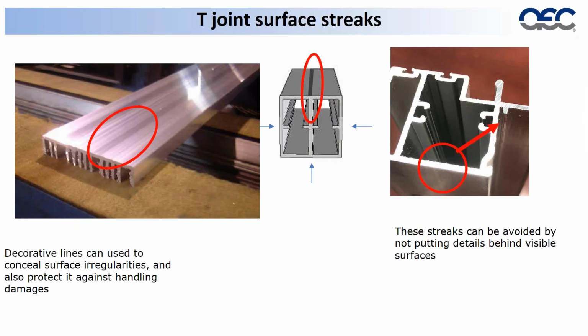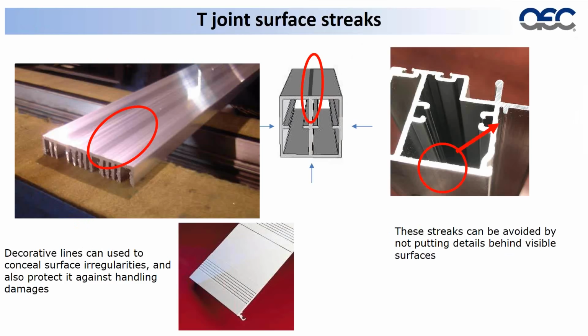And if you absolutely have to have the leg behind a visible surface, what you can do is use decorative lines. You see here what we've done inside this lower red circle is put 4 or 5 features into the extrusion, and these hide rather nicely those issues that are going on behind. So there's lots of things, but as Rick said, we have 45 minutes and we've eaten up quite a bit of that already. We'd like to give you 2 practical examples of things that have been done.